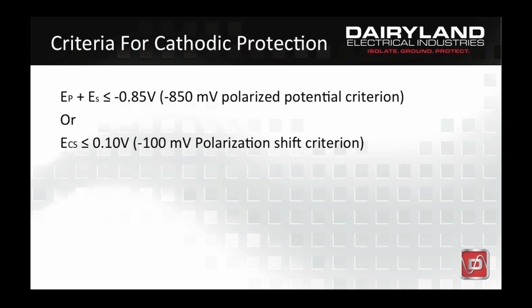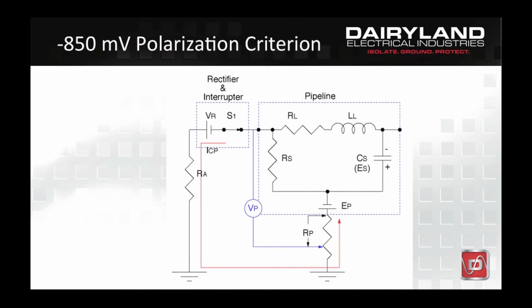When decouplers are used on poorly coated structures or poorly coated pipelines and close interval surveys are conducted, the measuring error under discussion does not normally exist because such pipeline circuits have a very low RC time constant, which will be explained later. A pipeline is considered adequately protected if the 100 millivolt shift criterion is met, even though the minus 850 millivolt criterion may not be met.